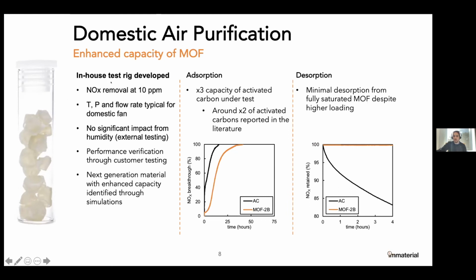Alongside that, we developed a test rig in-house for looking at this NOx filtration. We were working at 10 ppm, so probably a lower concentration than those that are typically reported in the academic literature, but much higher than ambient levels of NOx that you might be concerned about. Beyond that, we're working at temperatures, pressures, and flow rates that would be typical for the domestic air cleaning fans, which are the intended devices for these materials. We looked at the impact of humidity as well, although we had to do that externally. We couldn't build that into our rig, which was really focused on this quick iterative testing.